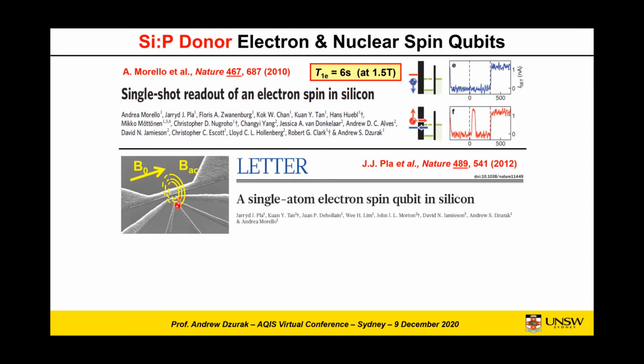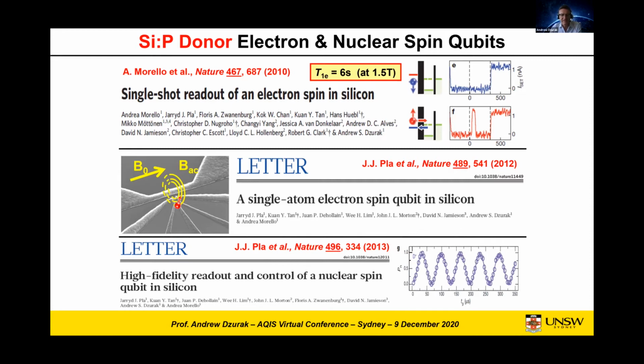So returning to this paper published 2 years later, what our groups showed, and this work was really championed by Andrea Morello, was that it was possible, having readout in place, to employ a microwave AC magnetic field. This is in the gigahertz regime, tuned to this Zeeman energy splitting, and it was possible to demonstrate Rabi oscillations in the spin of an atom bound in this nanoelectronic device. And then just 1 year later, and the PhD student who worked on this, Jarryd Pla, is now, I should mention, a faculty member at UNSW.